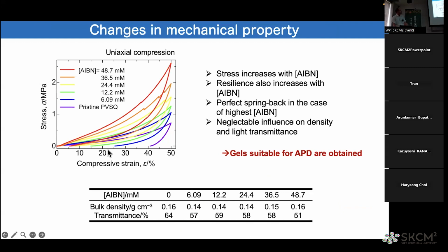So these are the stress strain curves by uniaxial compression of the gels treated with different concentrations of AIBN, which is a radical initiator. With the highest concentration of AIBN, the gel is very stiff, like this, and shows spring back like this again. But the pristine PVSQ, from the same precursor gel, shows rather weak, soft mechanical property and limited spring back behavior. After the treatment, it is very hard with perfect spring back because of the hydrocarbon chains.